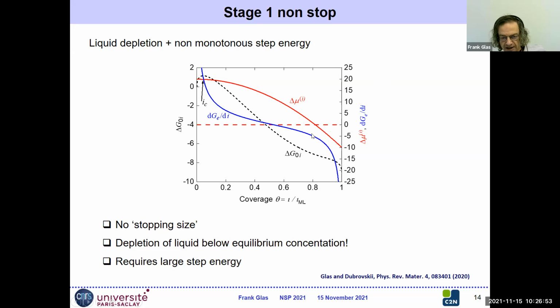In other words, the stopping size may be suppressed in this case. Well, all right. An interesting consequence of this is that because there is nothing to stop growth, the liquid can go below equilibrium with the solid phase, which would be this dashed curve. If you want to understand this, it's simply that because the step energy now decreases with the number of atoms we add to the step, it becomes interesting to add atoms, not only because of the chemical potential effect, but also because it increases the surface of the step and decreases the total step energy. So we can deplete the liquid below equilibrium.